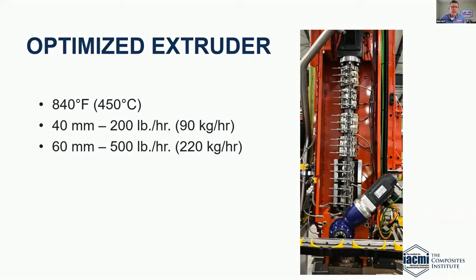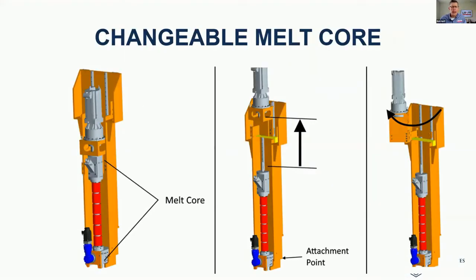And what's different about this is that most of the other extruders that are used in the plastics industry use friction to add heat to the plastic as it's being melted. Whereas this really uses the screw as a conveyor and adds almost all the heat with heating jackets on the outside. Very interesting, and it makes for a very consistent process. Another thing that's interesting about it is that it was originally designed so that it was easy to swap melt cores. If you have a really large high temperature application, you can use a larger melt core. And then you can simply slide the servo motor up, disconnect the electrical and mechanical connections, pull out the melt core, and put in the other size melt core.